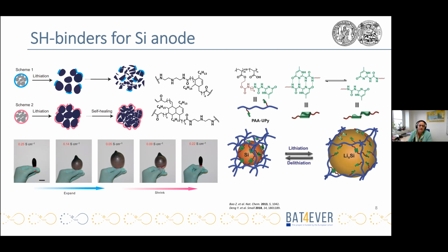When we look at the previous research and the literature regarding the self-healing binders for electrodes, everything has started with the pioneering work of Bao and co-workers in 2013, and this inspired the worldwide research of self-healing binders for silicon anodes. They used reversible hydrogen bonding of urea groups to create a self-healing polymer binder, which, in contrast to the classically used binders, was able to compensate the internal mechanical stress caused by the volume changes of the silicon microparticles while still remaining conductive and autonomously repair the micro cracks which were appearing during the cycling of the battery, and hence significantly increase the lifetime of the silicon anode.